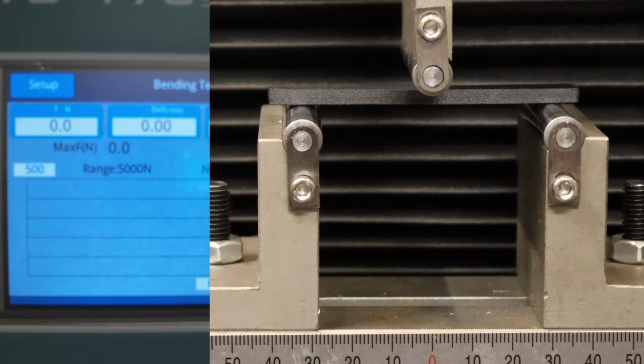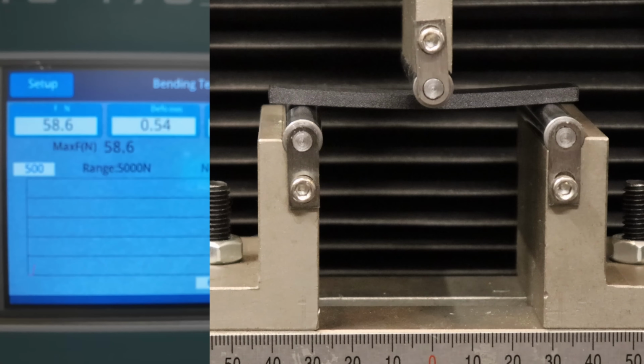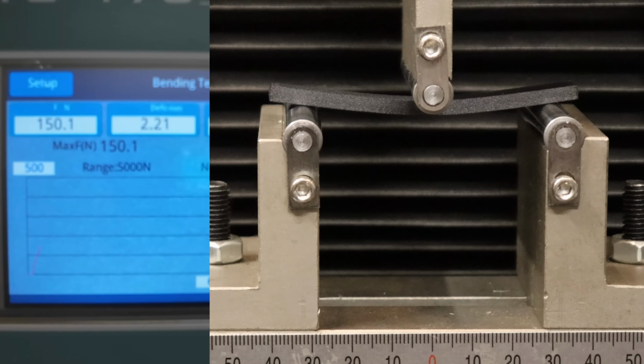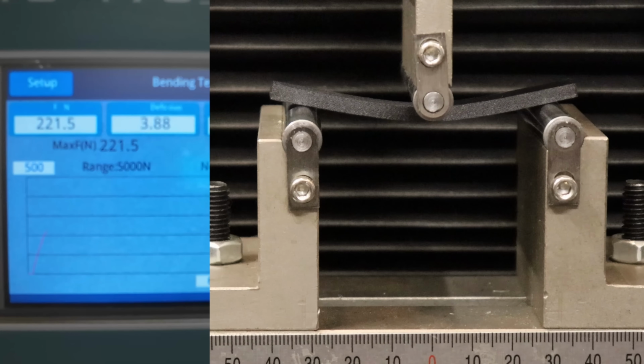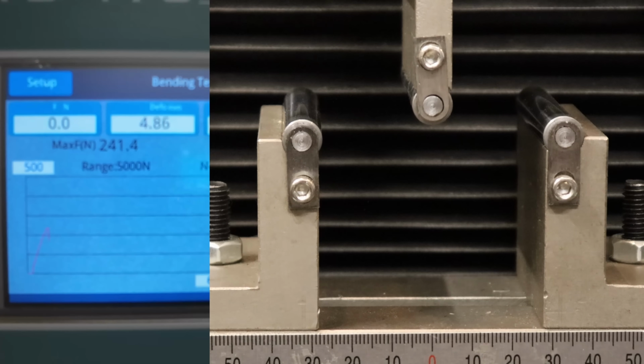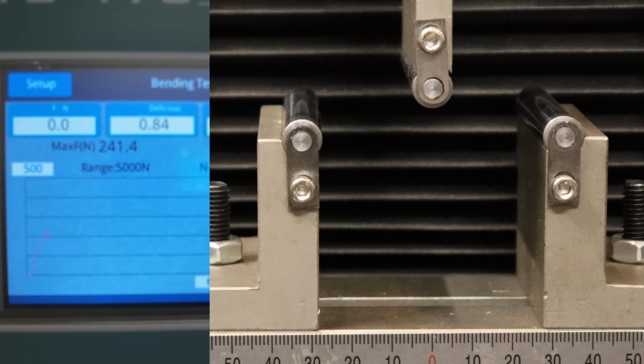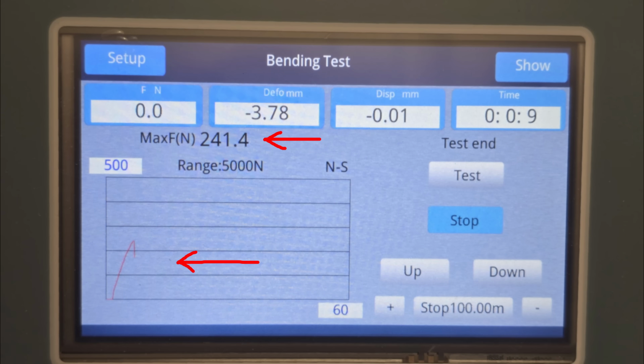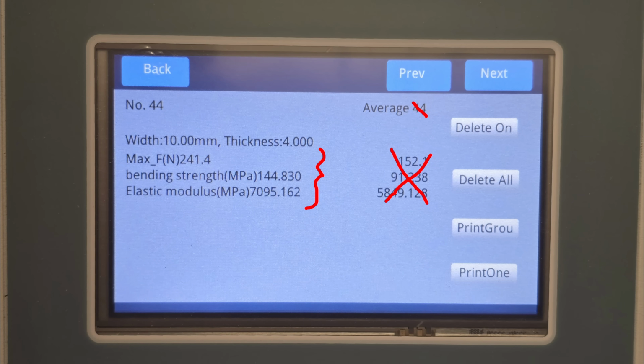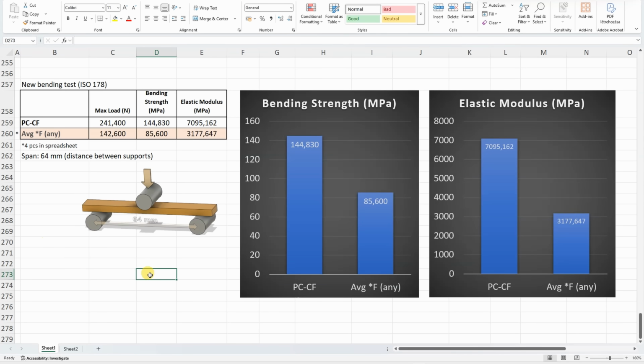Another bending test in my universal testing machine. Distance between supports is 64 mm, and this is real-time speed. It breaks very suddenly. You can see here the graph and the maximal load, bending strength and elastic modulus. This is a relatively new test for me on this channel, and I have only 4 fiber reinforced filaments in that summary table, and it will be used in this comparison. And we can see that this PCCF is extremely strong, both in bending strength and elastic modulus.